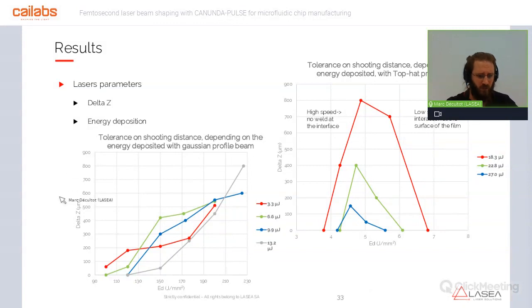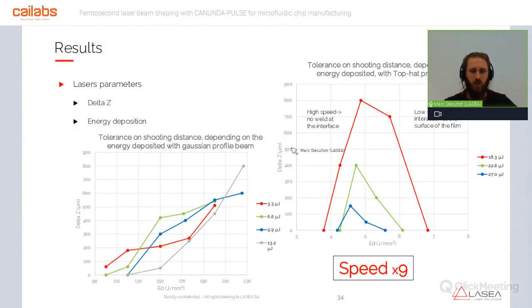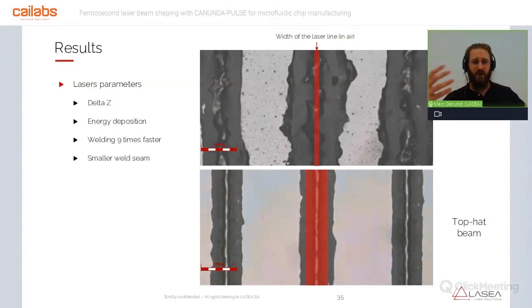At the left, you can observe our result with a Gaussian profile, and at the right part of the slide, our result with a top hat profile. We see that even with a higher energy per pulse in the case of the top hat profile, we need a lower energy deposition to achieve equivalent results. What it means is that we can use a higher speed to achieve a good welding quality with a top hat profile. So our welding is faster with a top hat beam, but we also observe a smaller weld seam. Here you can observe a welding seam with a Gaussian beam, and here a welding seam with a top hat beam.